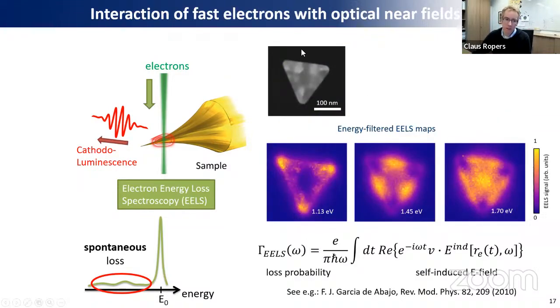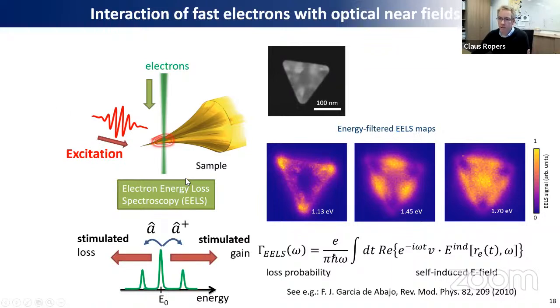Also for these nanotriangles, for example, you can get characteristic scattering probabilities, so loss distributions at different energies, and they directly represent the optical modes, the plasmonic modes of such structures. Now, what we can do in the Ultrafast TEM is not only look at the emitted cathodoluminescence or the spontaneous loss distribution, but we can also use the optical excitation to populate a particular mode and then study the scattering probability. So essentially the description for this is relatively straightforward. It's just computing the probability that an electron gains or loses energy by interacting with the time-dependent field projected onto the electron trajectory.